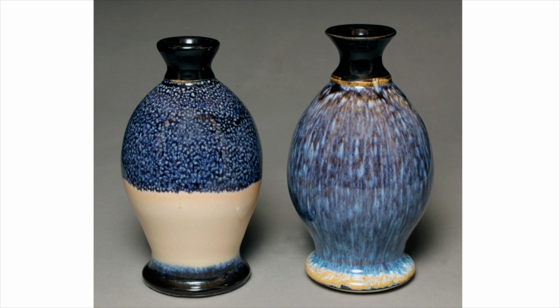These two bottles were glazed with the same glazes at the same time and fired in different kilns to cone 6. The bottle on the left was fired using the slow program, and the bottle on the right was fired using the slow program plus a down firing. I love to use a down firing with all my firings.